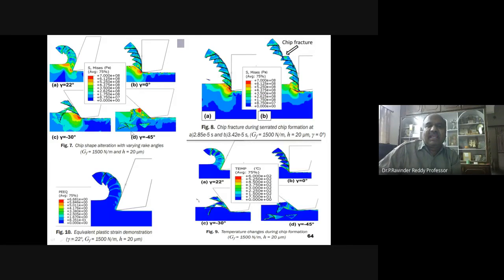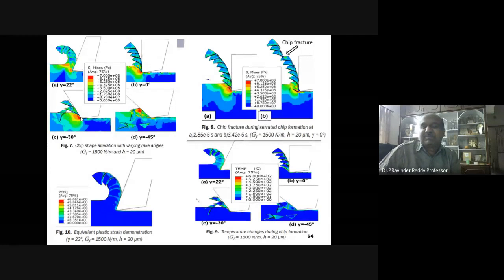And here, again, with constant energy and constant depth of cut, changing rake angles: at zero rake angle you have this pattern. At 22 degrees, you have a continuous chip, and again, there is a breaking somewhere. And at minus 30 degrees, you can see it is again coming back, and there's no continuity. The minus value is not a real simulation of how the actual work progresses in experiments.